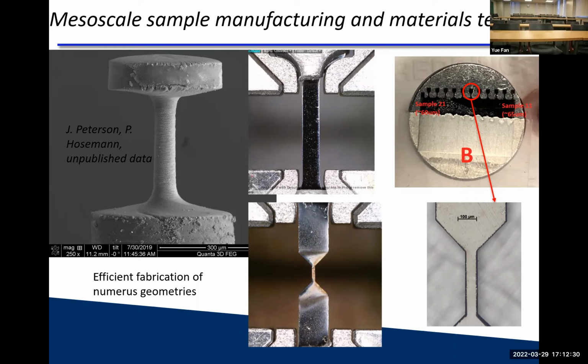Helium implantation, we did an indent, for example, and what you see is helium bubbles sort of lining up all the way in that shear zone, which is very different from the crystalline version, right? Because you're not going to see that in the crystalline version at all. And the reason we think it happens is the hypothesis for why you have these localized shear bands in BMGs: you usually have heat development in the deformation. People say you can get quite high temperature, and the thought is that maybe that makes the bubbles grow locally. That's why they line up that way in these zones. But I don't know, it's very new, and we haven't really done too much other than the experiment.